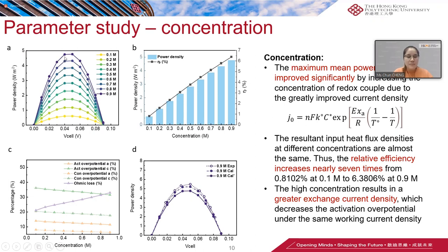The effect of concentration on the performance of thermal cells is shown in figure A. It shows the power density as a function of concentration and working voltage. So you could see that the maximum mean power density is improved significantly by increasing the concentration of the redox couple, due to the greatly improved current density. It is quite reasonable to predict the ascendant current density with increased concentration based on the concentration dependent kinetics.